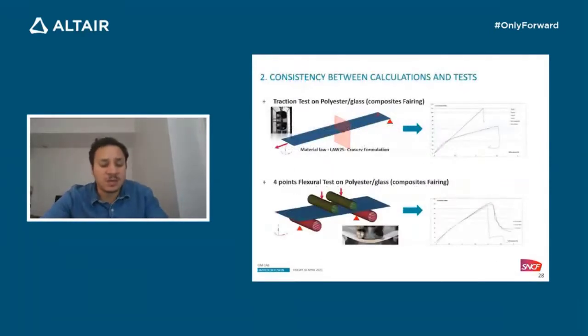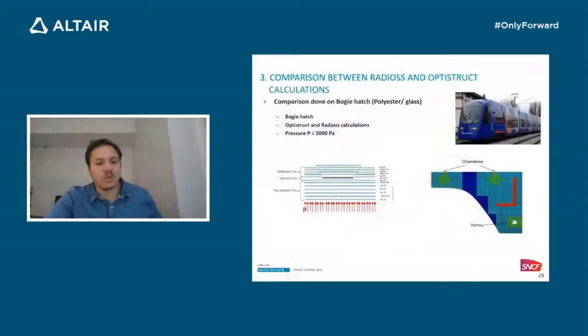At the beginning, it is necessary to obtain some parameters of the composite, like Young's modulus in fiber direction and so on. We obtained them for polyester glass used on train fairing. One of the tests we wanted to correlate is the traction test. With that, it was possible to adjust non-linear parameters. The same was done with the 4-point flexural test.